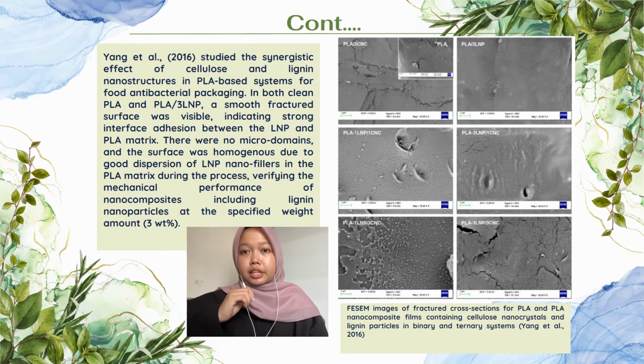A study by Yang showed the synergistic effect of cellulose and lignin nanostructure in the PLA-based system for food antibacterial packaging. The surface morphology of samples shattered in liquid nitrogen and gold sputtered was used to investigate the microstructure of PLA and PLA nanocomposite film.